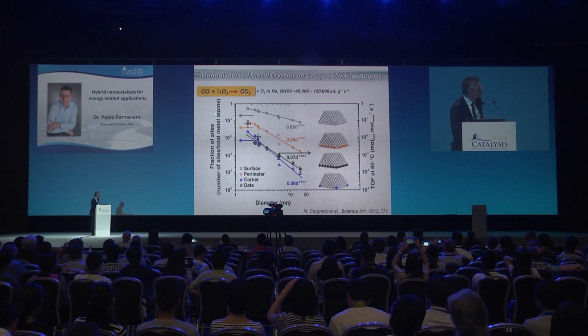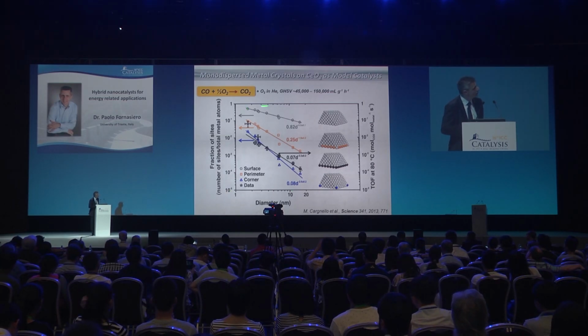So having this precise type of material, we were able to correlate the fraction of sites with the diameter. This is the correlation of the surface atoms with the diameter. This is the correlation of the fraction of atoms at the interface with the diameter, and this is the atoms at the corner at the interface with the support.